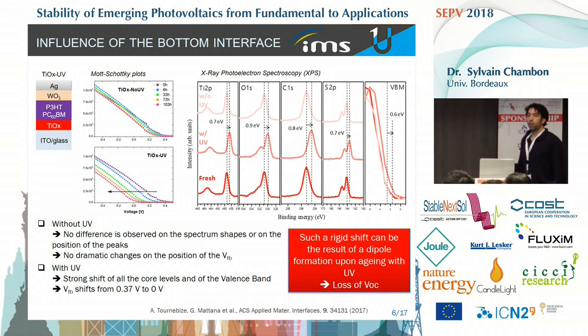We also studied in parallel some thin films of P3HT:PCBM on top of titanium oxide, which we aged under inert condition. And we studied the evolution of the different peaks corresponding to the oxide, but also of the active layer. In the case of titanium oxide-based samples, we observed, only when UV is present, rigid shifts of all the core levels of the titanium oxide, but also of the organic layer. We also observed a shift of the valence band maximum.